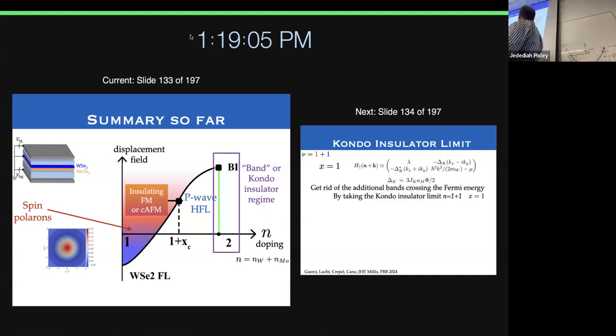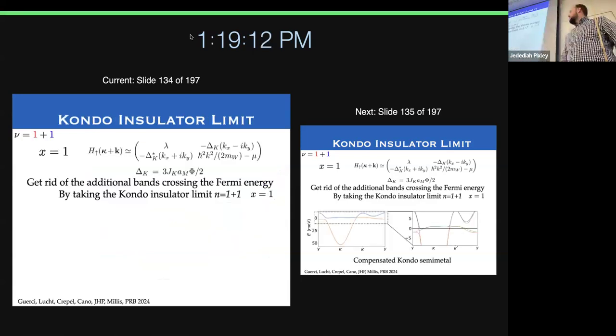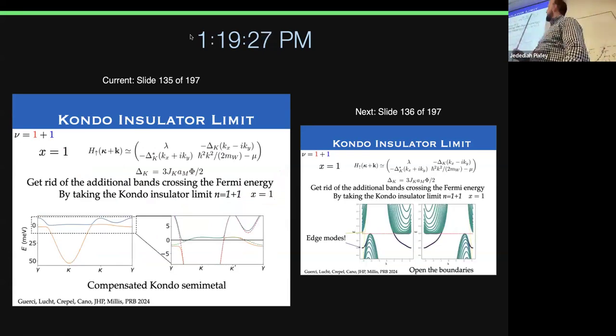And I was alluding to this limit near 1 + 1 as being interesting. So if we go to 1 + 1, we knew this actually when we first wrote the paper, but we didn't think it could be done experimentally. And then we heard at the previous March meeting it could, and they were doing it. So I'm going to show some data that's not out yet. Okay, but so now if I go to 1 + 1, I get a Kondo compensated semi-metal. So I have electron hole pockets that are compensated.